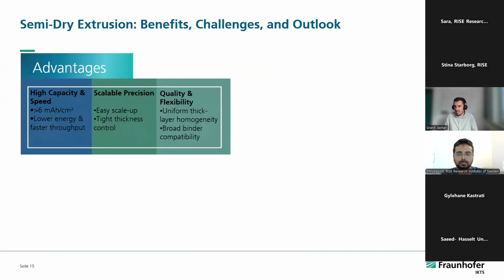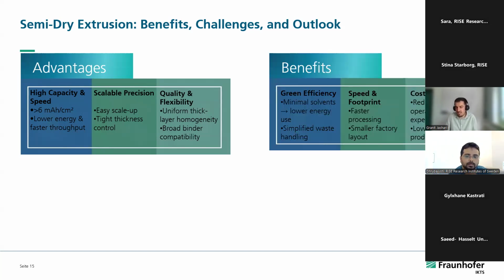What I would say as the advantages, as I said, we could go to really high capacity electrodes, and also the speed. It has low energy consumption on the drying, and it's easy to scale up. It still has tight thickness control compared, for example, to dry technology, where film thickness control is still a challenge, but here it is not, since we are still using a slot die.